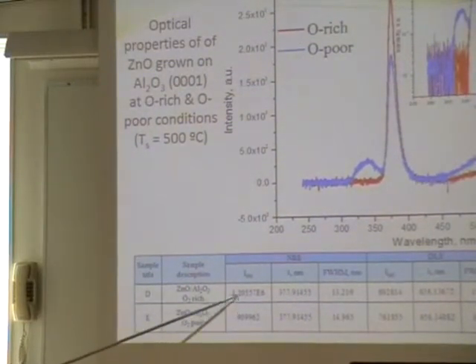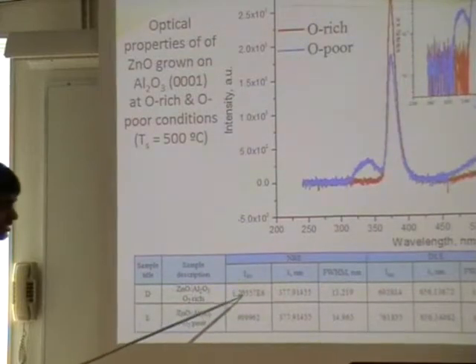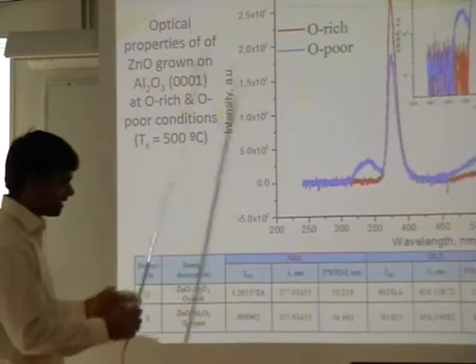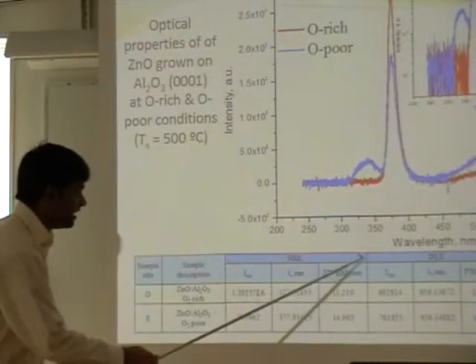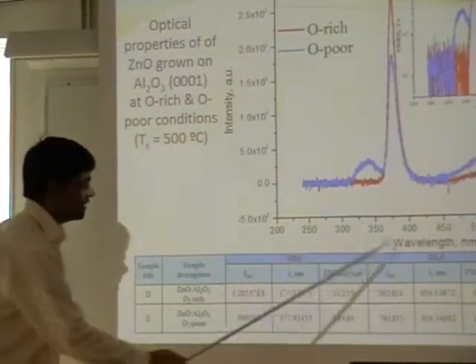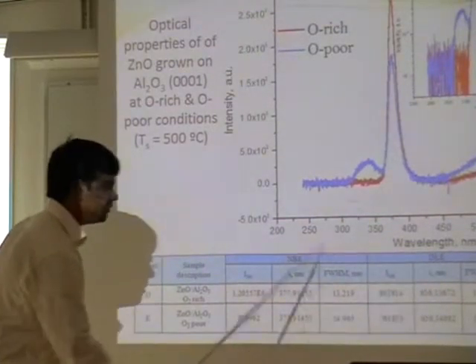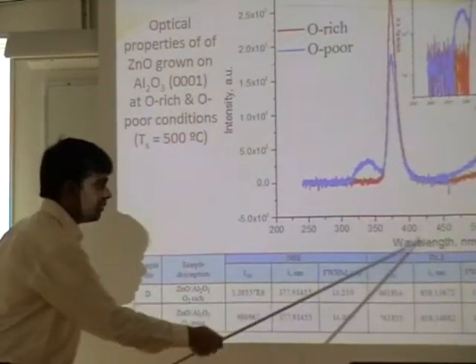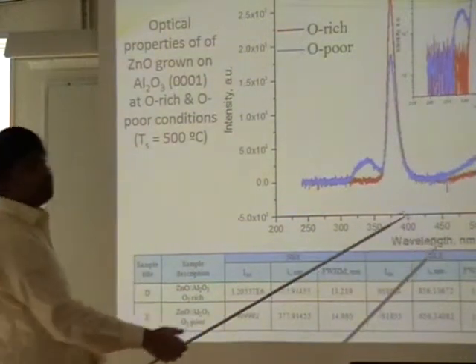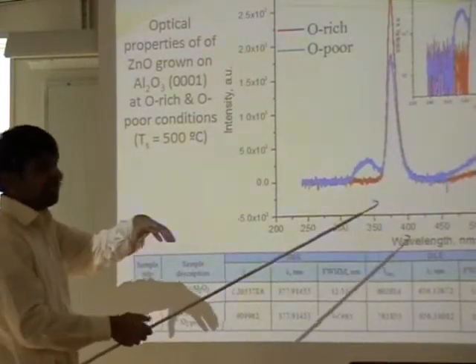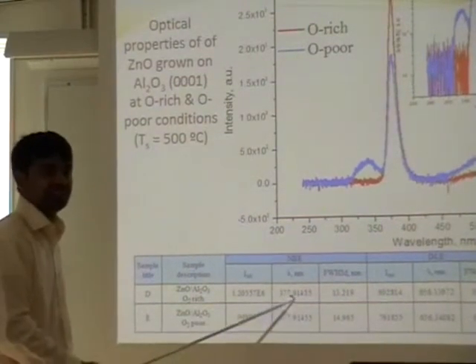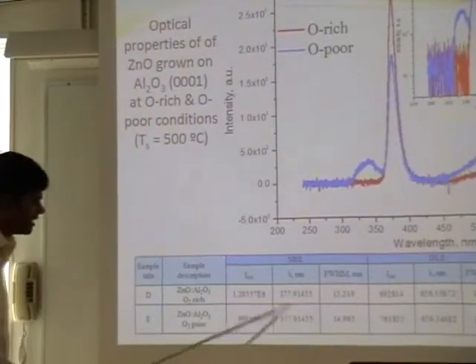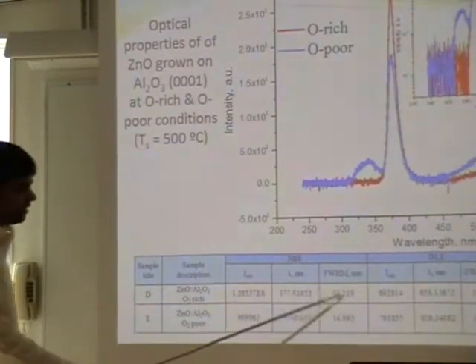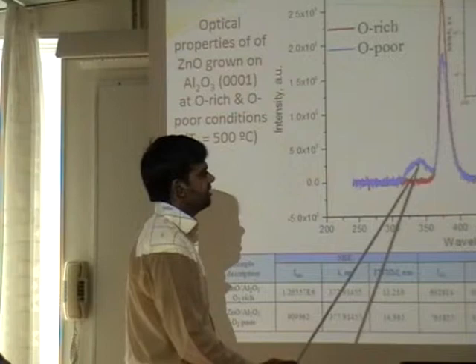In the oxygen rich case, the intensity increases and the full width at half maxima decreases in near band edge emission. But in deep level emission, it becomes opposite. It means we are not interested in deep level. Although deep level emission has much prospective property, we are interested in near band edge emission. You can see not so much effect on it. These peaks, I'm sure, are from the sapphire, that is from the substrate.